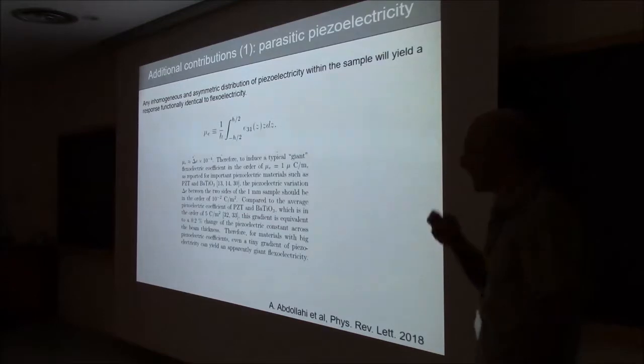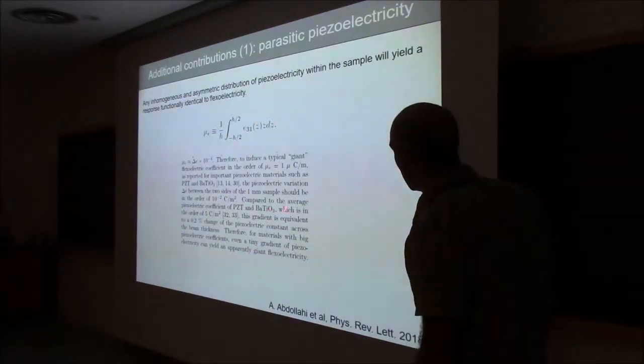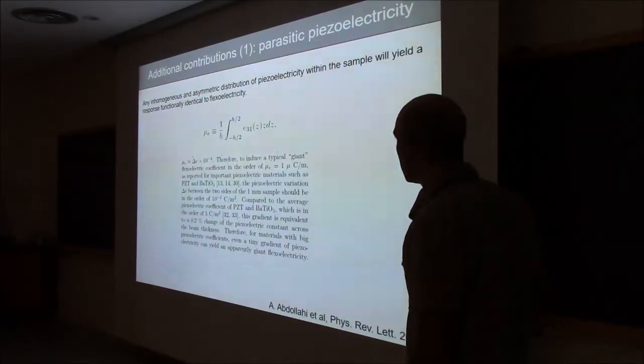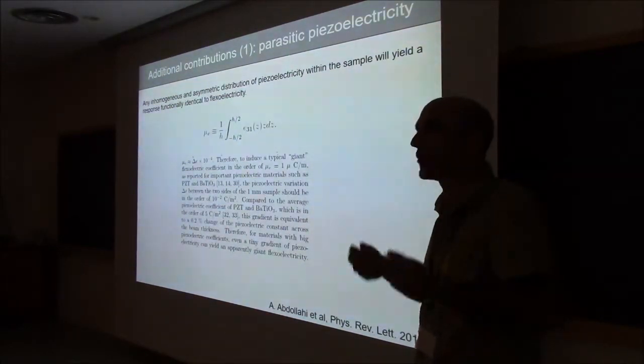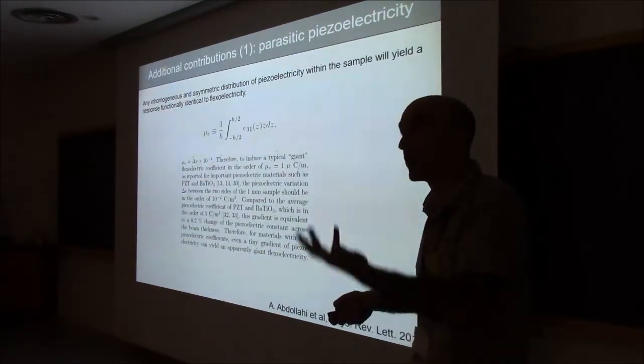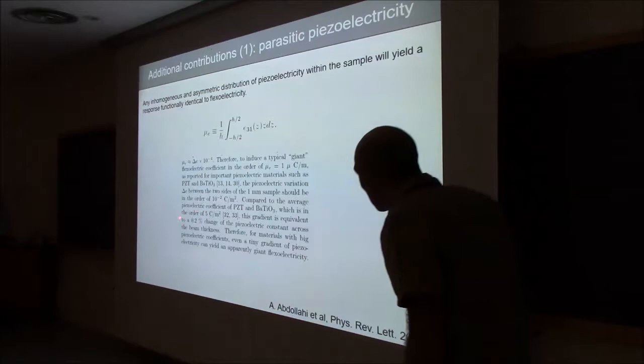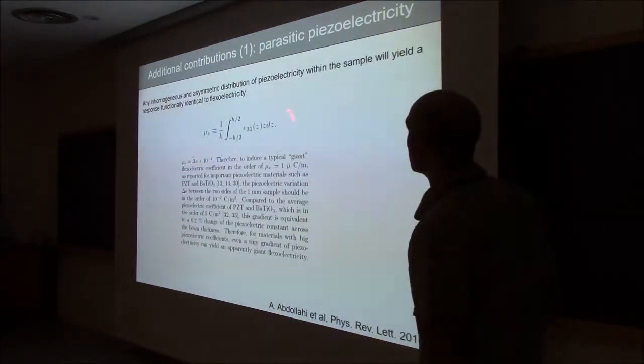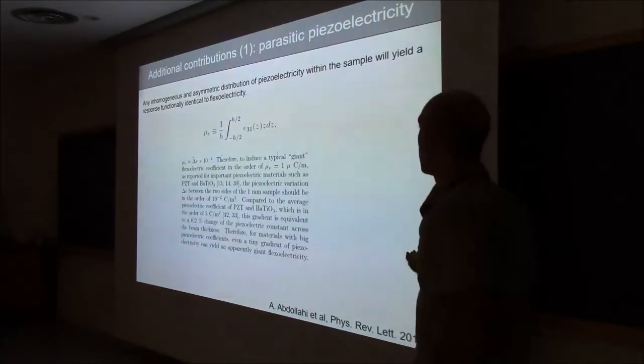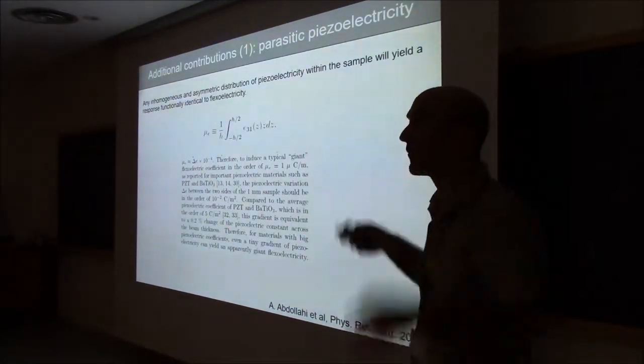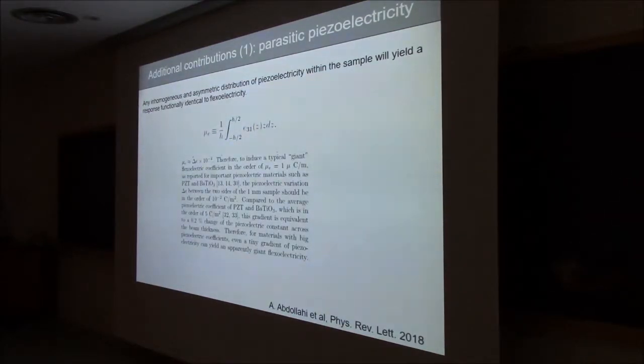That sounds all very abstract, but what it boils down to, if you want to put numbers, is if you take BTO or PZT and you have a 1 millimeter crystal and try to bend it, which is what we typically do in our DMA experiments, if you have just a 0.2% difference between the polarization at the top surface and the polarization at the bottom surface, that is enough to give you an effective fake flexoelectric coefficient of the order of microcoulombs per meter. So already 1,000 times bigger than what we would measure in STO. Okay? What it boils down to is, if your material is ferroelectric or piezoelectric, you have no hope of measuring the intrinsic flexoelectric coefficient in the polar phase.